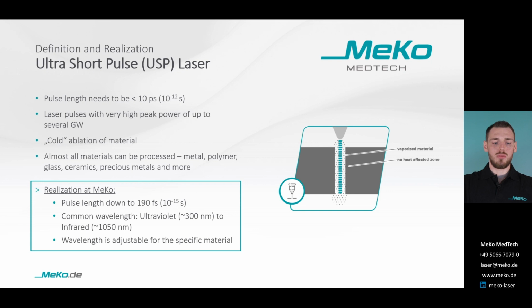Besides polymers, almost all materials can be processed like metals, ceramics, or even organic materials. At MeKo, femtosecond laser systems are used with pulse lengths down to 190 femtoseconds. The wavelength is adjustable in a range from ultraviolet at around 300 nanometers to infrared at 1050 nanometers. The wavelength must be carefully selected for the respective material. This depends, among other things, on how well the material can absorb the radiation at the certain wavelength.